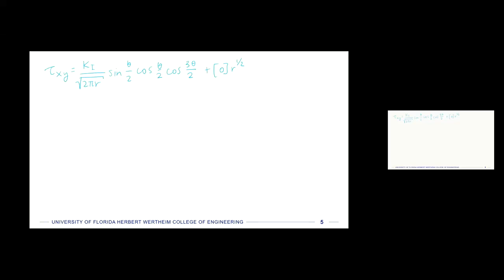Okay. And so I said I'd come back to sigma z. So there is no applied stress in the z direction. There is only a combination of stresses in x and y. So we're just going to say that it's the Poisson's ratio. So we're going to go back to kind of Hooke's law here. So it's the Poisson ratio times sigma x plus sigma y. So that'll be our sigma z. The other shear stresses are 0, so tau xz, tau yz, those are 0. So this is our plane strain conditions, and then these stresses at that crack tip.